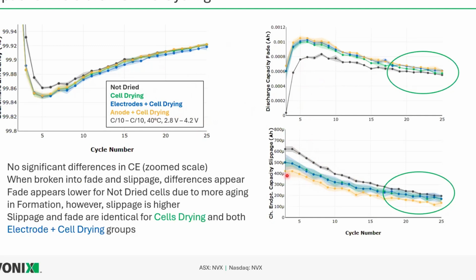And so I mentioned that was an important note earlier. And digging back through what was done when we dried the electrodes, what we found was that when we dried all of the electrodes together, all of the electrodes, the cathodes and the anodes, were put in the same vacuum oven. So as we're extracting all of this moisture from the anodes, in that same environment at elevated temperatures, these cathodes are getting exposed to that moisture.